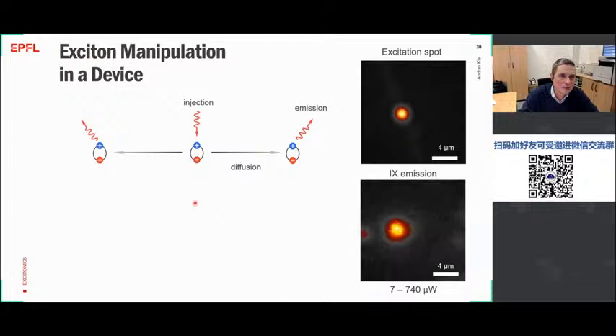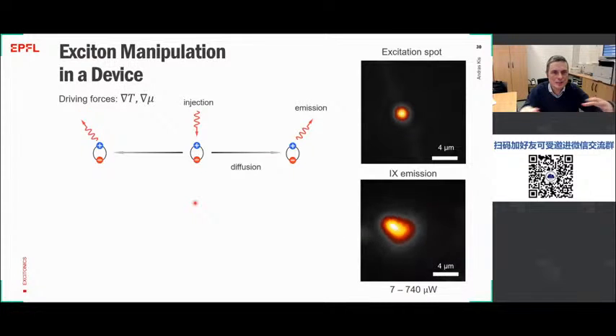Now, the driving force for this diffusion of excitons is the temperature gradient. Since we have a laser, we're slightly heating the sample under the laser beam, so there the temperature is hotter, and the excitons are flowing to the colder regions. And the excitons, since they are also electrical dipoles, there is an electrostatic interaction which is repelling them. So they kind of squeeze in one place. They would like to spread out to minimize the electrostatic interaction. So that gives rise to a chemical potential gradient, and the excitons would like to diffuse again away from the injection spot to minimize their energy. So these are the driving forces.